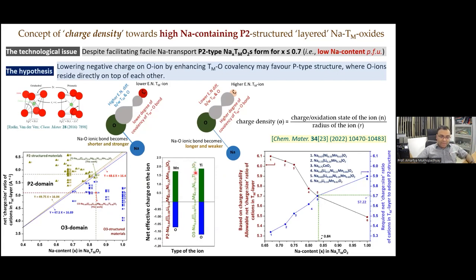So titanium 4+ having a lower charge to size ratio, because the titanium 4+ is bigger in size compared to manganese 4+, will lead to lesser covalency of the transition metal oxygen bond and lead to greater effective negative charge on the oxygen ion, and that leads to an O3 type structure. Whereas if we have manganese in place of titanium, it leads to lesser effective negative charge on the oxygen ion, and so the oxygen ions can sit one on top of each other and lead to a stability of the prismatic coordination, and we can have a P-type structure.